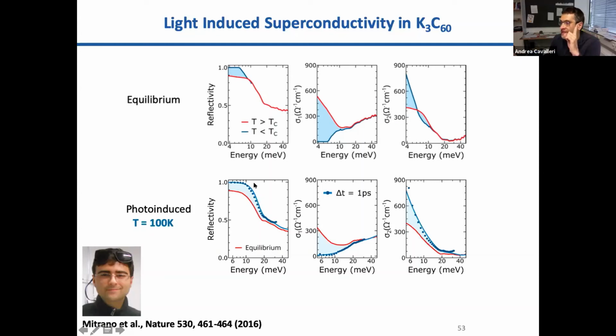So the only difference that you see here is that the gap appears to be larger than the one that you have at equilibrium. Although the sigma 2 divergence, which tells you how strong the density of Cooper pairs is at 0 frequency here, or how dense the superfluid is, is about the same. So this was really a striking, at least it was very exciting for me when I saw this.